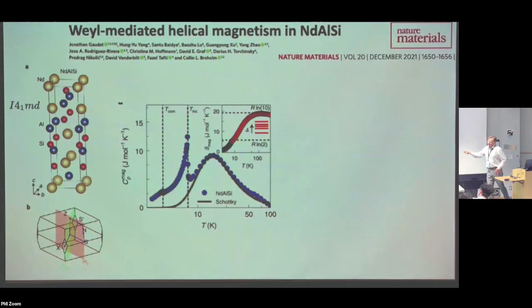It's also quite normal to eventually get a transition to the commensurate state, because the incommensurate structure cannot produce a full magnetization of the spins. If I have this kind of periodicity which is not commensurate with the lattice, I can't get every spin to be fully magnetized, and that's energetically very unfavorable at low temperatures. And so there's almost always a transition into what some people call a squared-up structure. You get some kind of square wave formation, which then becomes commensurate. In this case, it is a commensurate structure, but with a bigger unit cell than the chemical unit cell. So this is what happens, and it's not particularly unexpected.